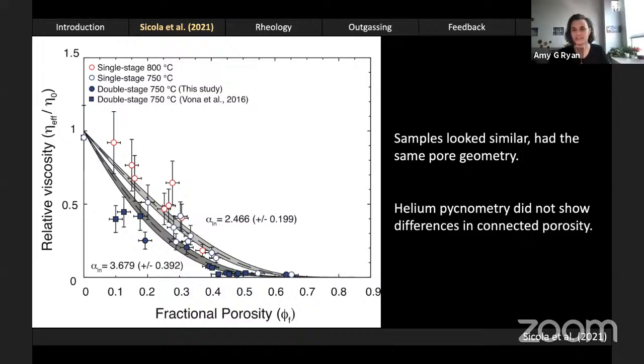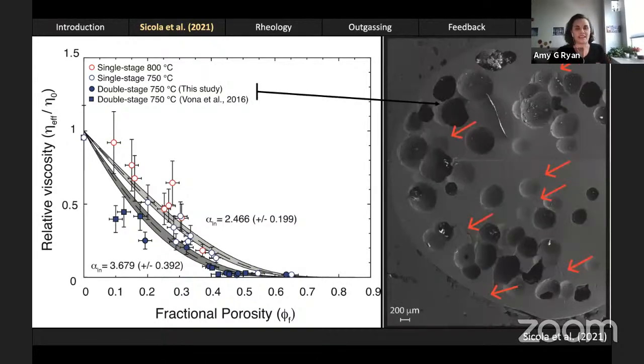The samples look the same, they have the same pore geometry, they're vesiculated melts. And helium pycnometry, a technique that we often use to look for connectivity of pore spaces in experimental or natural materials, didn't show any difference in connected porosity between the two experiment subtypes. So what she did then is the first stage of her double stage experiment. She heated the sample, allowed it to foam, quenched it, and then instead of deforming it, she cut it open and looked at it in the SEM.